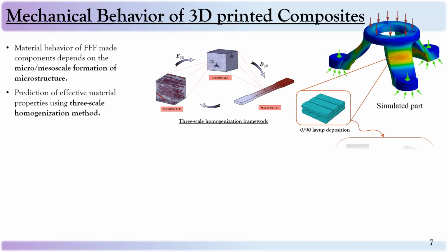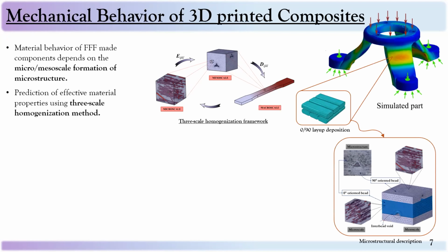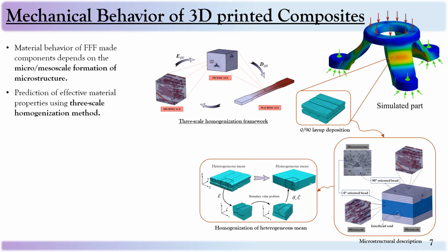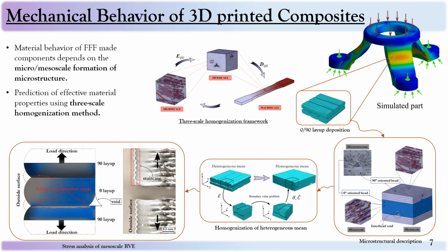And you can see the microstructural description over here, which will lead us to perform a homogenization process using the RVE, representative volume element method. You can see that the direction of fibers changes on the 0 and 90 layup direction. So we perform a homogenization process to get an effective property for neat ABS and carbon fiber reinforced ABS materials. And overall, in this way, we can interpret the failure mechanism under tension and compression loads, after performing stress analysis on microscale and mesoscale geometry.